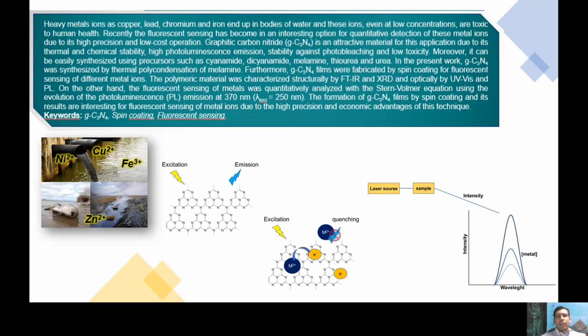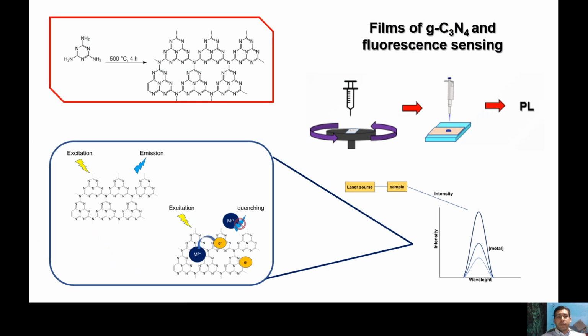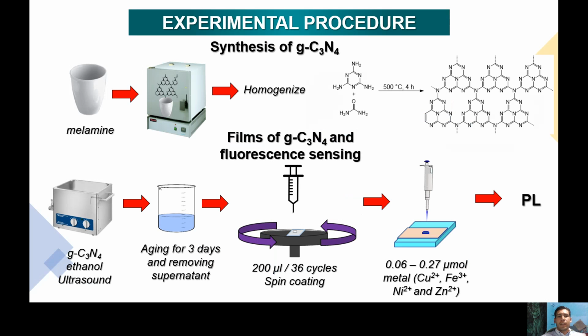One of the more important materials in this field is graphitic carbon nitride because it presents thermal and chemical stability, high photoluminescence emission, and stability against photobleaching. In this project, we made the C3N4 by thermal polycondensation, and with this material, we made films of the C3N4, and we use these films for fluorescent sensing of some metal ions as experimental proof.